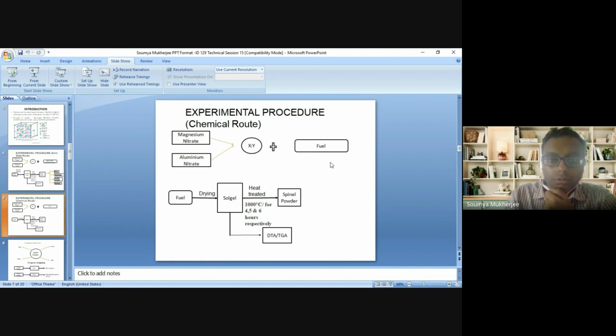For the chemical route, we have also taken AR grade, but this time nitrate as oxidizer in some molar ratio, that is 1:1, with fuel, which acts as a reducing agent and provides some energy. After mixing this fuel, we dry the sample and get the gel. Part of the gel is put for thermal analysis before the heat treatment, just like the previous one, so that our heat treatment schedule is not abrupt.